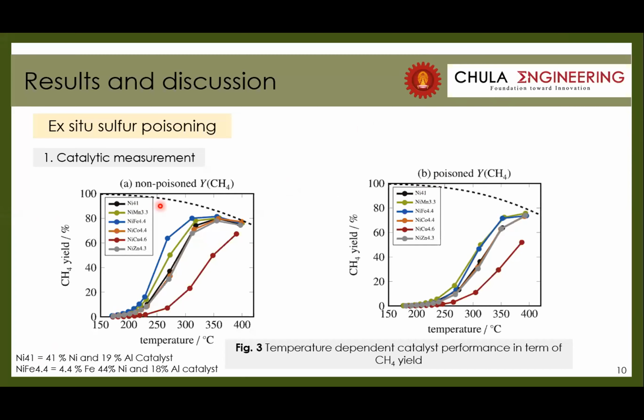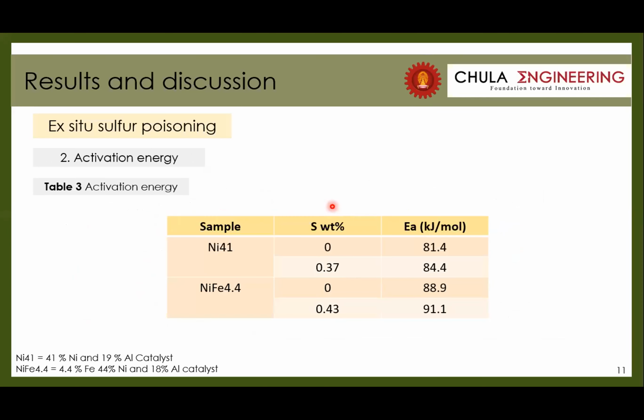And in this part, the ex situ sulfur poisoning catalytic measurement. In this figure, you will see that in the non-poisoned case or the poisoned case, the iron-promoted catalyst gives a higher methane yield, the blue line, than the methane yield of the unpromoted nickel catalyst, the black line. And this table shows activation energy. After poisoning, it is increased because the sulfur atoms block the active sites.